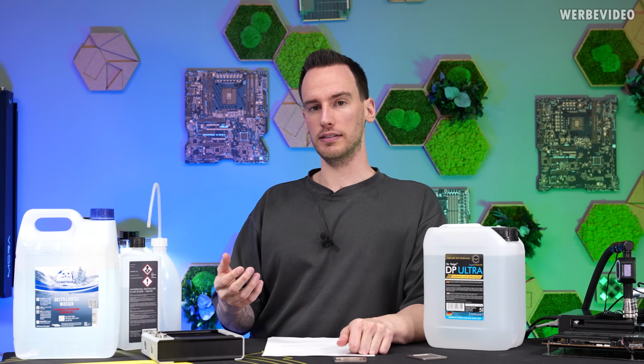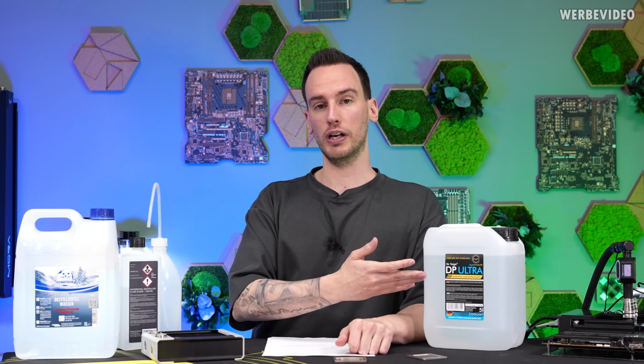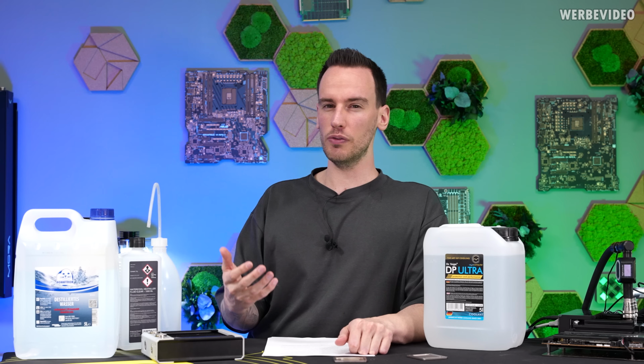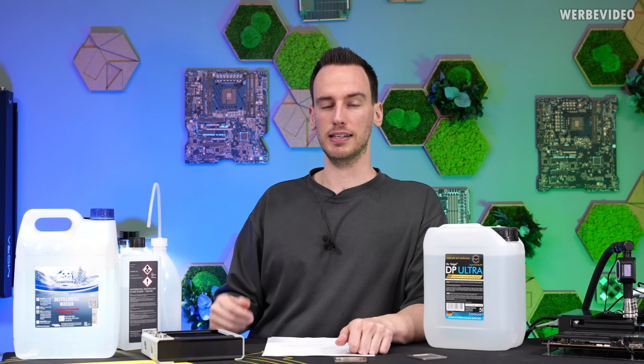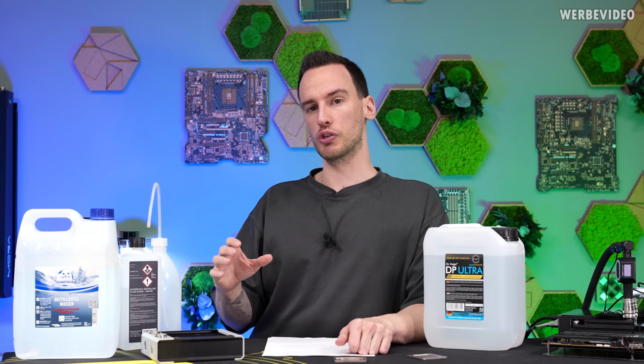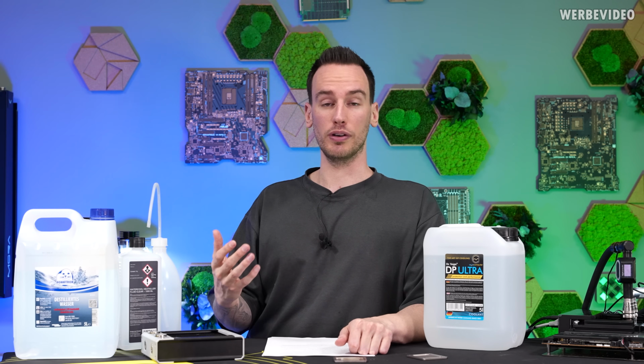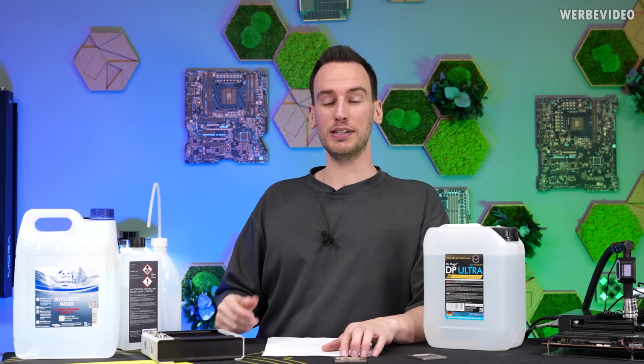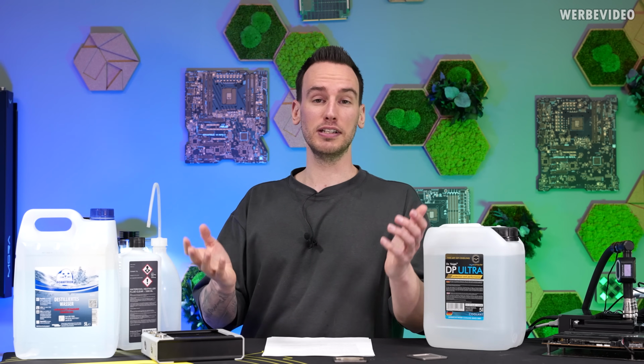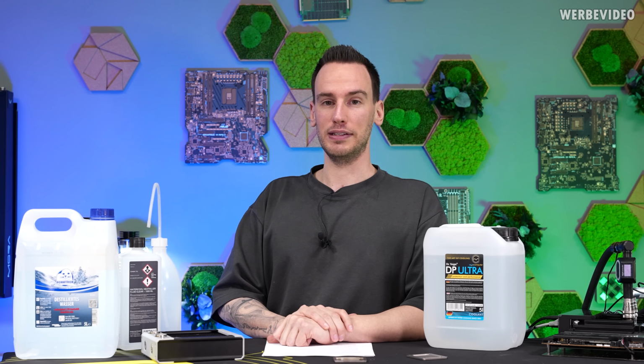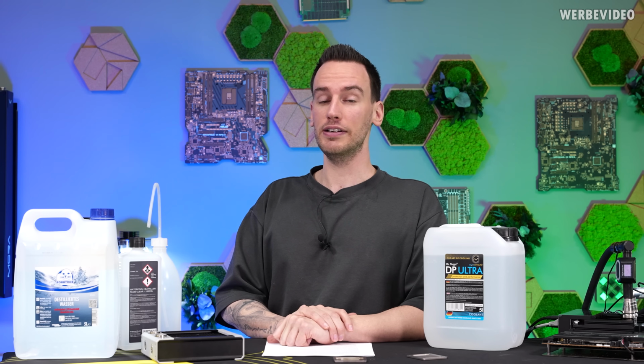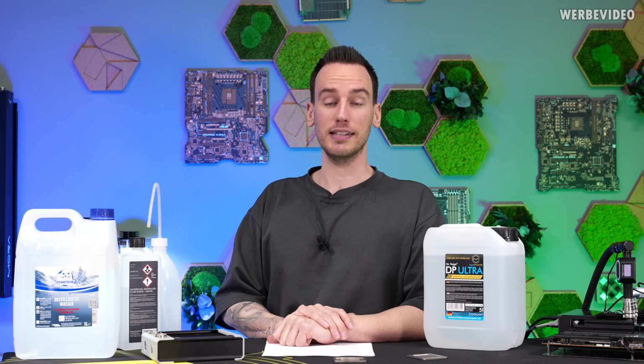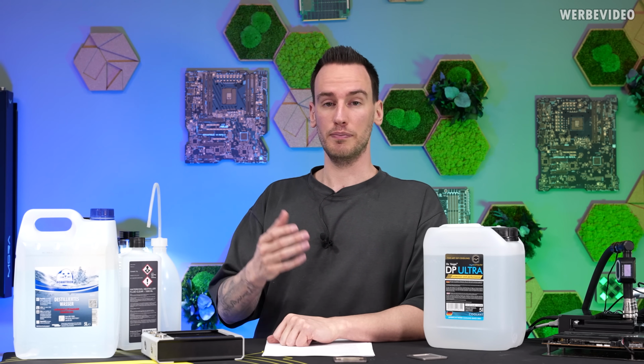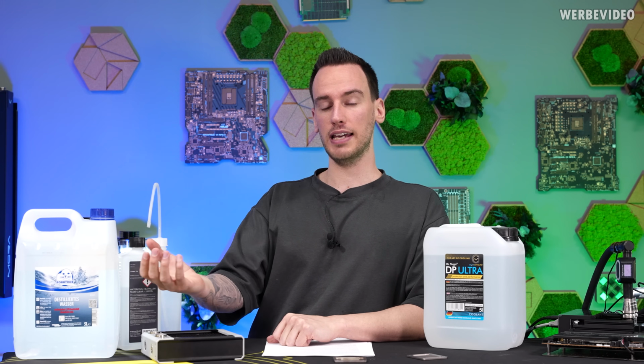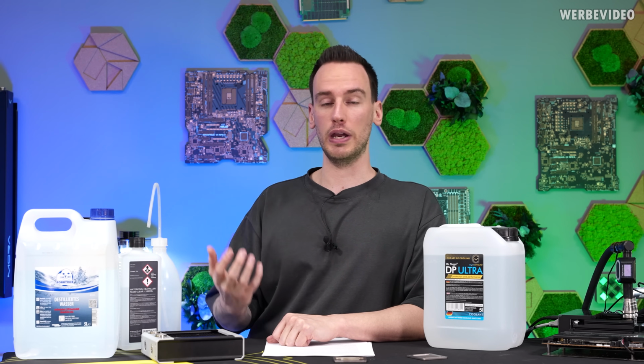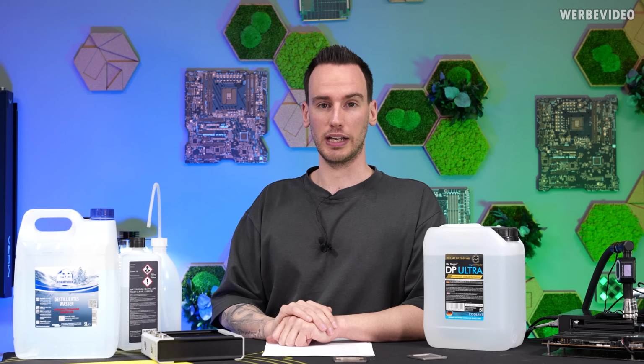One thing I also want to add is that those additives that are, for example, in the DP Ultra, they also degrade over time. So in theory, you would have to replace your liquid, let's say, once every 1 or 2 years to make sure that the corrosion is not occurring or is still very, very slow. So whenever you see the discussion again of somebody recommending just running distilled water without any additives, please send this video, because the distilled water, as clear as it is, without any molecules inside, that's exactly the problem. It is a polar liquid, which immediately takes up any ions out of anywhere and deposits them somewhere else because of the galvanic corrosion.